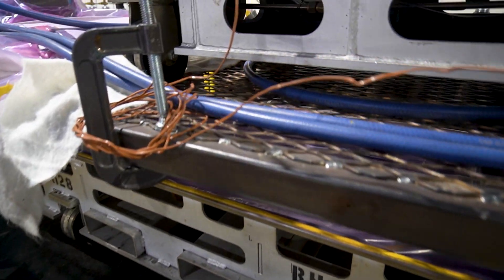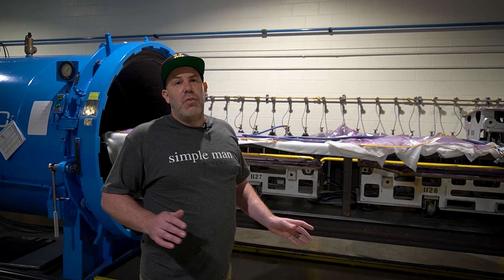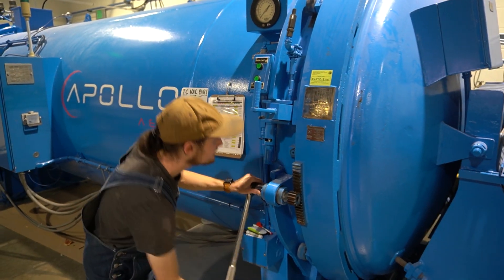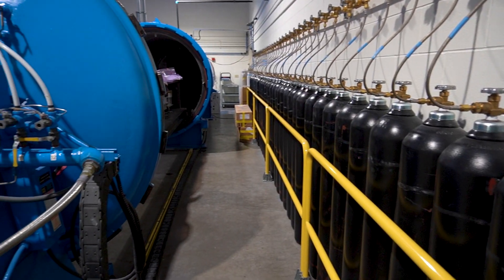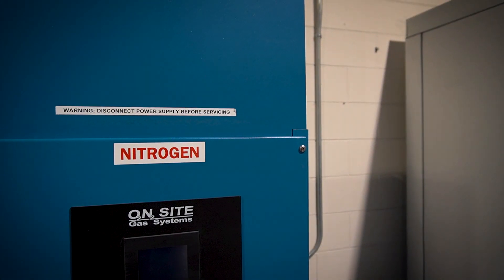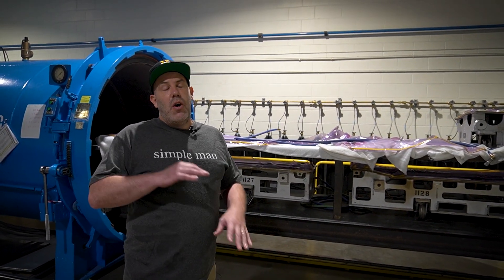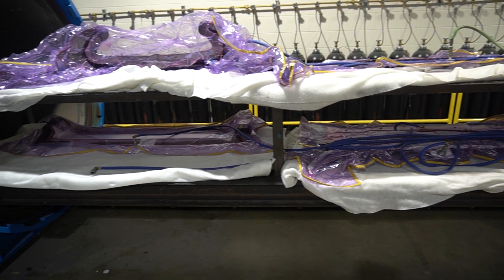This will ensure that when we're doing our cure cycle, whatever the lagging part may be — which will for sure be one of these steel molds — it'll ensure that it gets its full one-hour soak time. When we close this door, we kick a specific recipe we made, and it's going to kick the nitrogen on. We have a nitrogen generator over there — it produces the nitrogen and keeps it in storage tanks behind the autoclave. Once we kick on the recipe, it starts filling up the autoclave with nitrogen to whatever the recipe calls for. In this particular case, it's going to be about 90 to 100 psi, and it's also going to simultaneously ramp up to 250–260 degrees. Once all the tools inside the mold have hit the soak temperature, the soak time starts — so it's a guaranteed soak — and we produce our own nitrogen here.